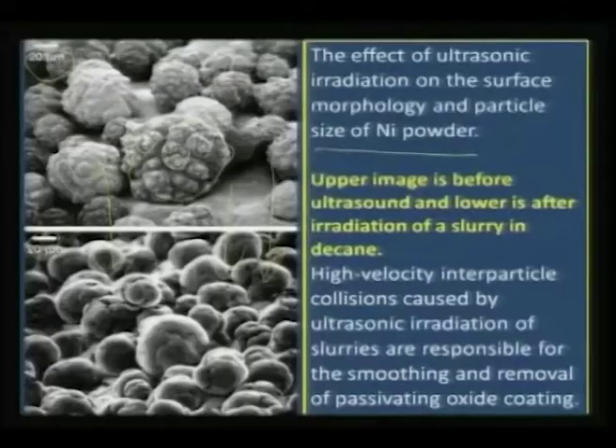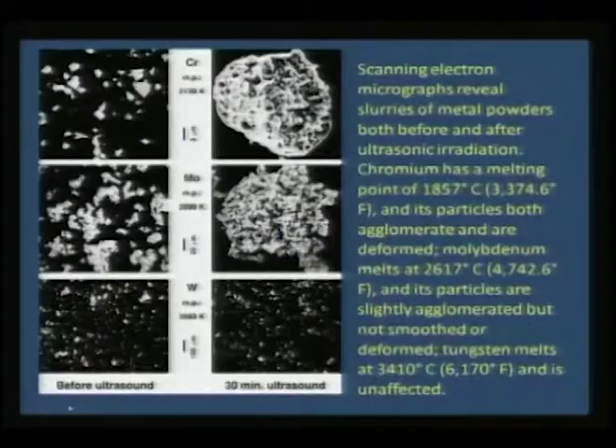So you do not need to go for a very costly nickel, you can just take a shelf nickel powder and do any sort of catalytic reactions just by surface treating it with ultrasound. What it essentially does is remove all the passivating layers of the nickel, whatever they are, carbonates, hydroxides, anything, or even the particle size can be broken into smaller ranges, and these are all nearly uniform. Therefore, one can say uniform surface-polished nickel particles become highly reactive, comparable to that of Raney nickel. So you can remove the passivation, you can really bring forth a variety of interesting features with ultrasound. Now, is that all we can see there?